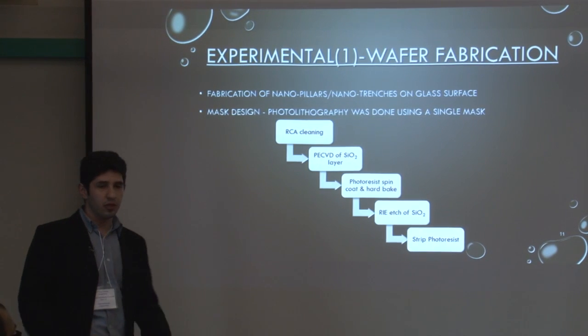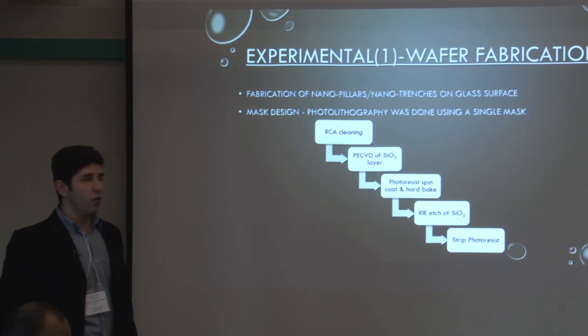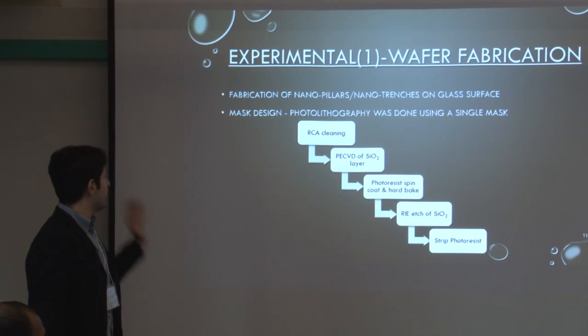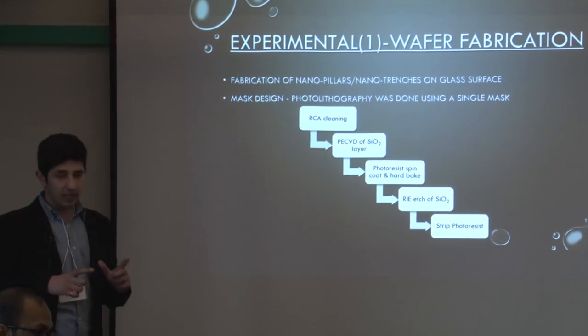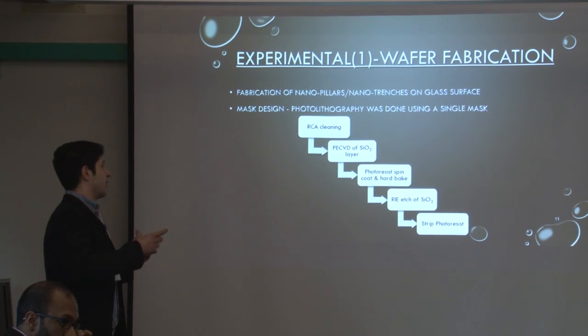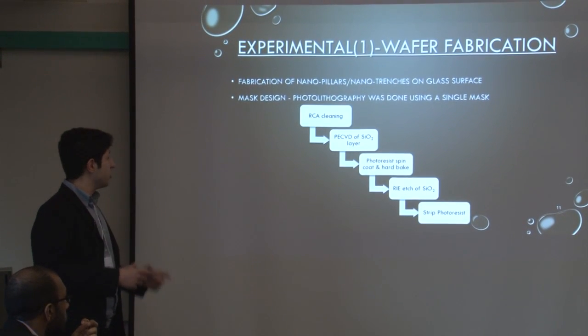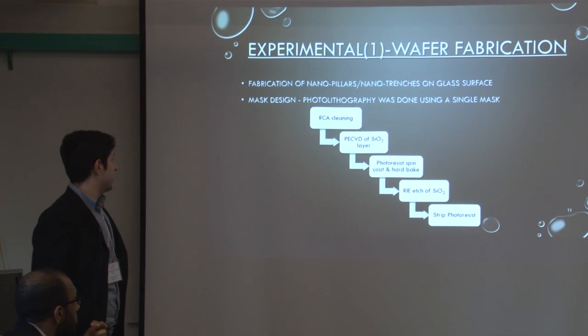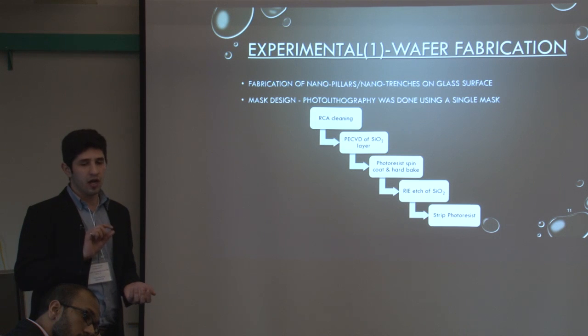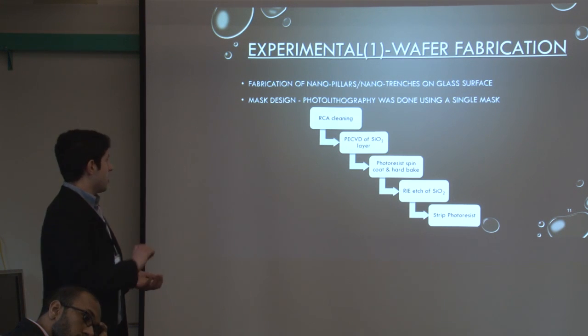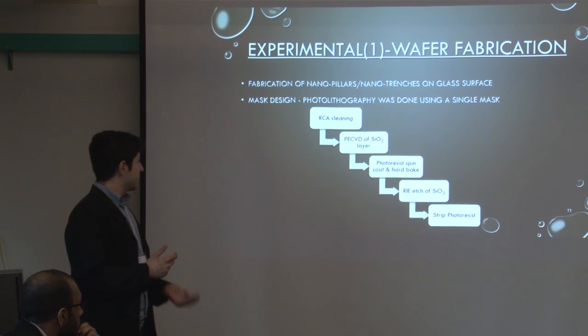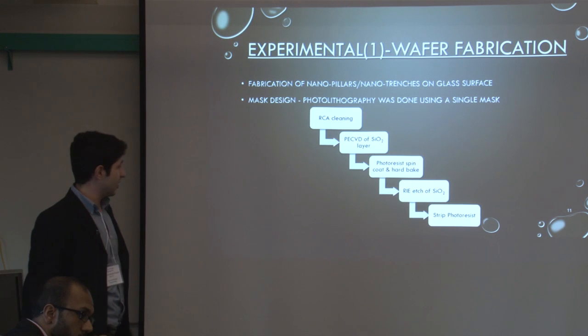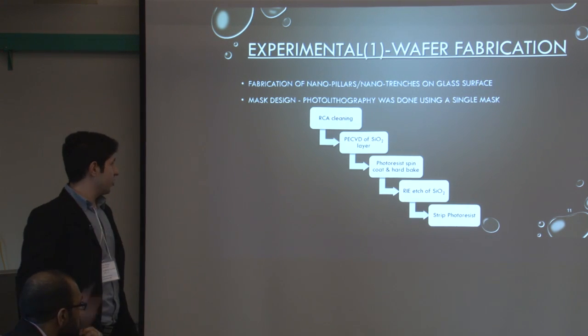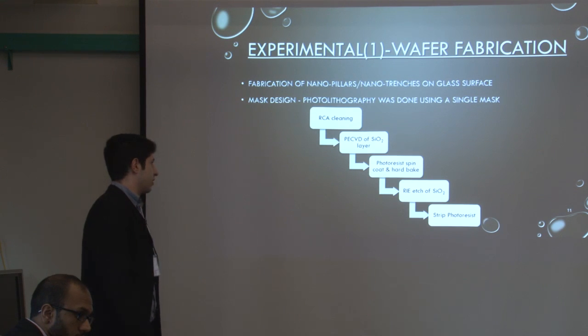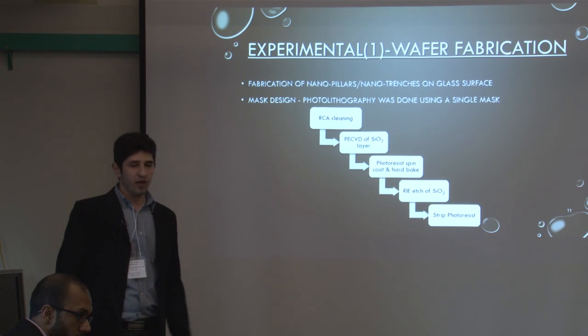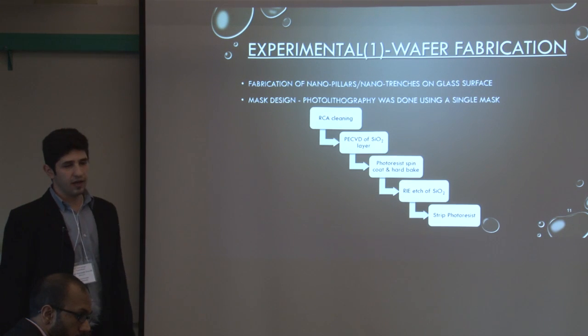So moving forward to the fabrication, in order to create these nanopillars, initially we created a mask. So we went through a series of techniques that were done in the clean room. After the mask was created, we started with clean blank glass wafers. We cleaned the wafers with the RCA cleaning technique, and then we deposited a layer of silicon dioxide on top of our glass substrate. Using the mask and photolithography techniques, we transferred the design from the mask to the glass substrate. We exposed and developed the surface, and then finally, using the reactive ion etching process, we created our nanopillars. And at the end, we stripped off the photoresist from the surface.